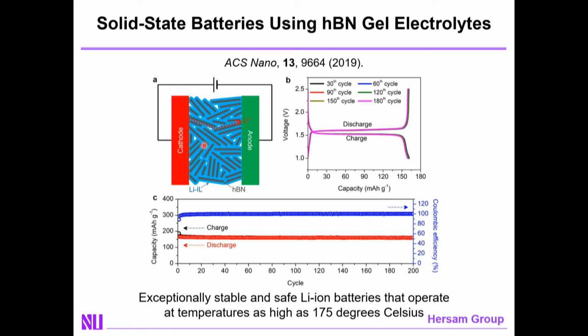The charging and discharging performance is highly stable with very slow capacity fade. Also, interestingly, these HBN ionogels, due to their high thermal stability, allow you to operate your battery at high temperatures up to 175 degrees Celsius.